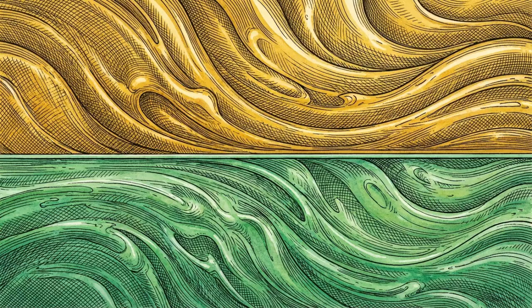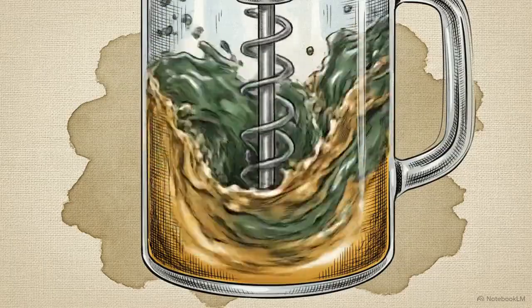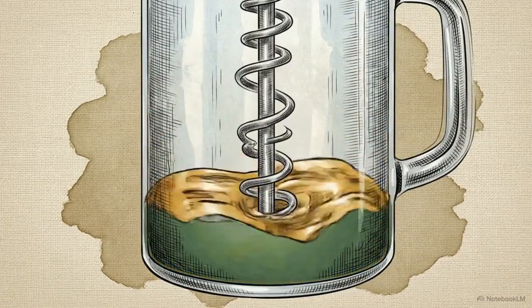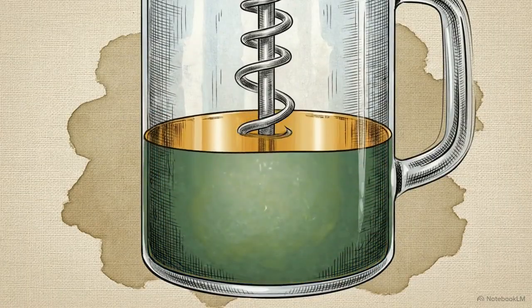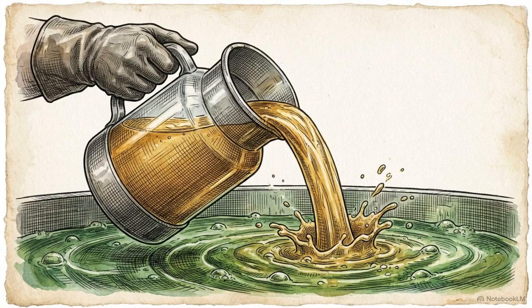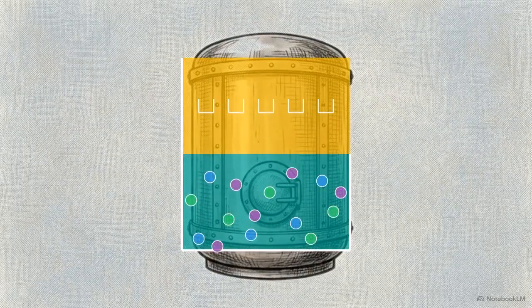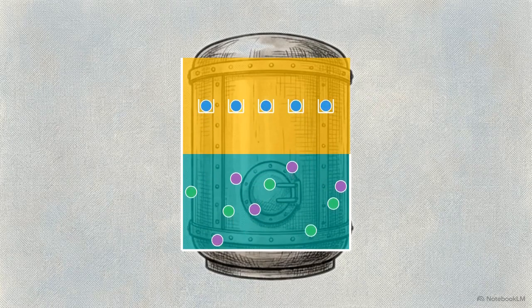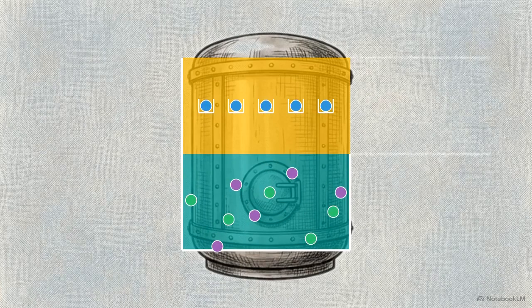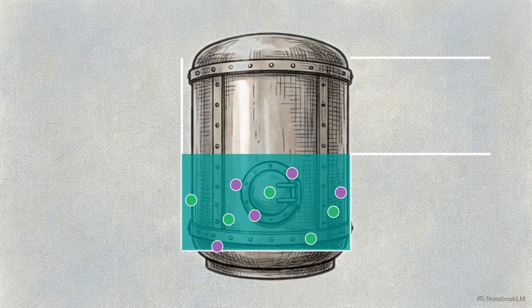This is achieved through solvent extraction, a highly sophisticated chemical process that relies heavily on liquid-liquid phase transfer to successfully separate the target metals. Recyclers introduce highly specialized organic extractants, specifically dialkyl phosphinic acids like Cyanex 272, into the aqueous PLS. These organic solvents exploit strict thermodynamic complexation preferences, engineered to bind to exactly one type of metal ion. For example, the extractant binds exclusively to cobalt ions, pulling them into the organic phase, leaving nickel ions trapped in the aqueous layer below. This requires a strict linear architectural sequence.